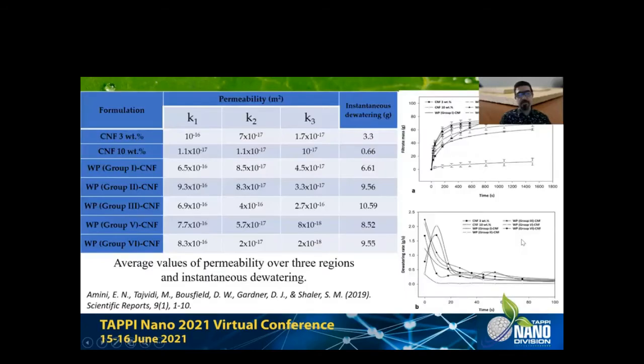All the nanocellulose is stuck in the system. So we recently published this work, which basically shows you how fast it is possible to dry or dewater nanocellulose in the presence of wood particles. So this is the curve for 3% CNF, and then these other curves are for when you add wood particles to it with different particle sizes.